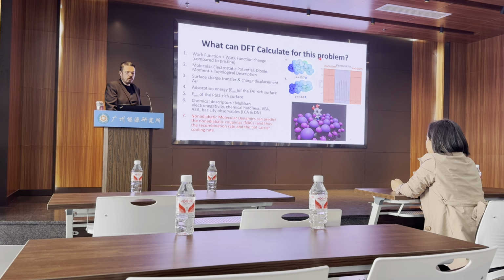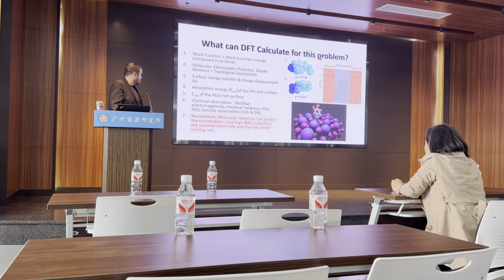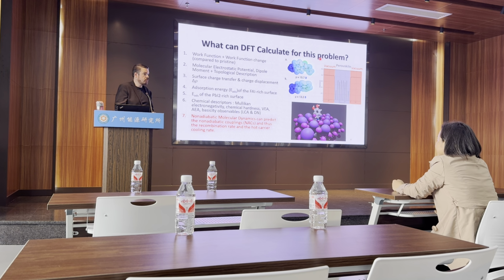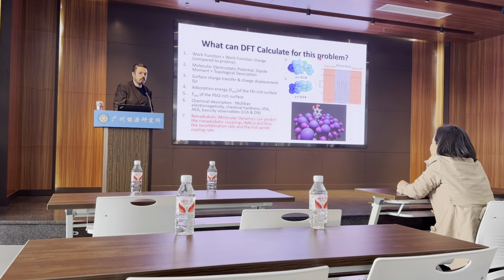non-adiabatic molecular dynamics. So this involves non-radiative recombination, but it's not limited to just non-radiative recombination. This gets into the very, very modern and new topic of hot carriers, because hot carriers are probably the future. If we can engineer the devices to take advantage of hot carriers, we can break the SQ limit. So this is huge. And here we can do both. We can do non-radiative recombination rates and hot carrier cooling rates.